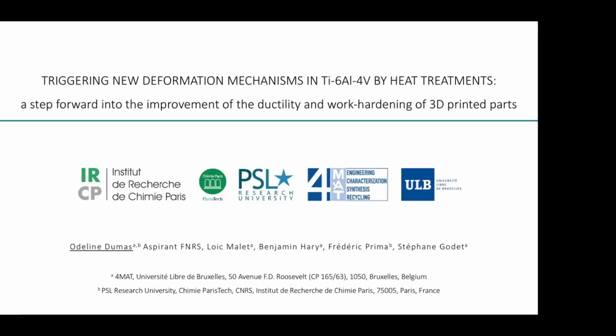Depends. You have to check the chemical composition because, for example, in our case, we tried some other heat treatment temperatures, and when you go to a higher temperature, your martensite will have more aluminum, and in this case we cannot see reorientation anymore. So we think that because of the chemical composition, you have this ability to induce reorientation or not.